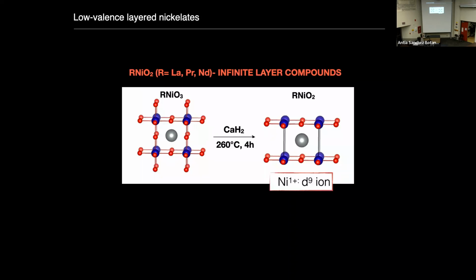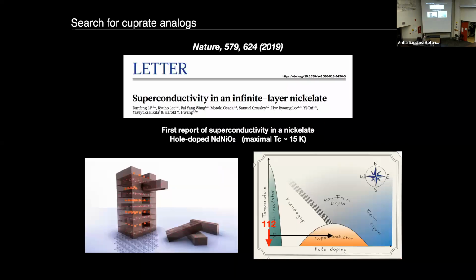If we do a simple ionic count in this material, R is a 3+ ion, oxygen is 2-. What you end up getting is a nickel 1+, that is a d9 ion, or a pseudo copper 2+, which is what we want. And the surprise came in 2019 when it was found that by doping, one can actually get superconductivity in these materials. This is work by Harold Hwang's group at Stanford. This was, as I mentioned in the beginning, the first report of superconductivity in a nickel oxide material ever. More specifically, the system in which they found superconductivity is hole-doped neodymium nickel oxide, NdNiO2, that has a maximum Tc of around 15 Kelvin. You may say, okay, it's not very high, but again, we'll see later that that may help us understand certain things that could perhaps help in pushing that up.